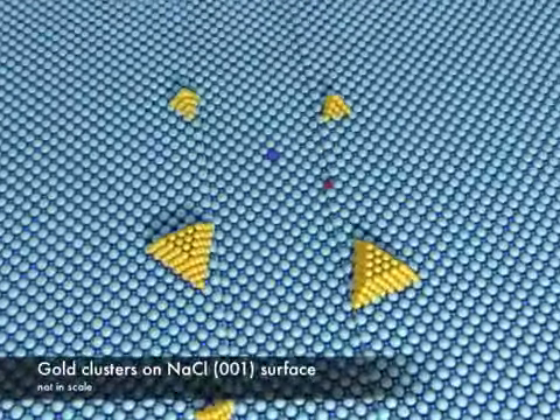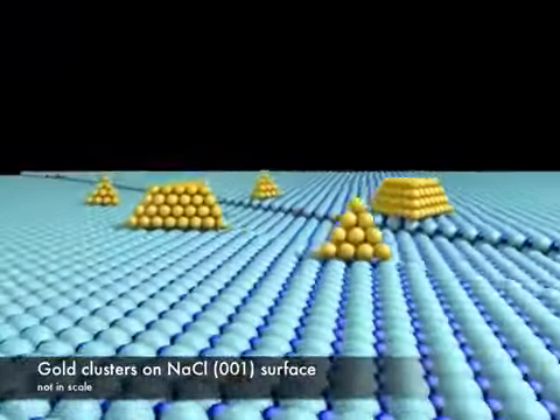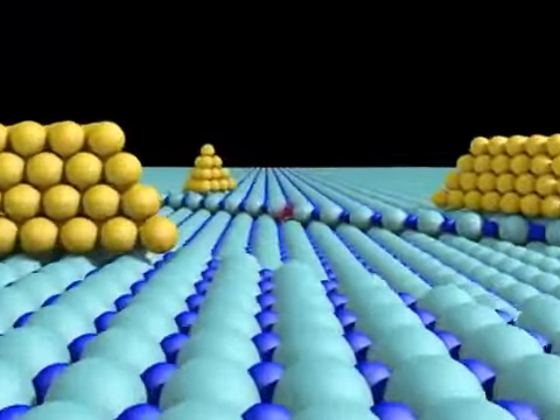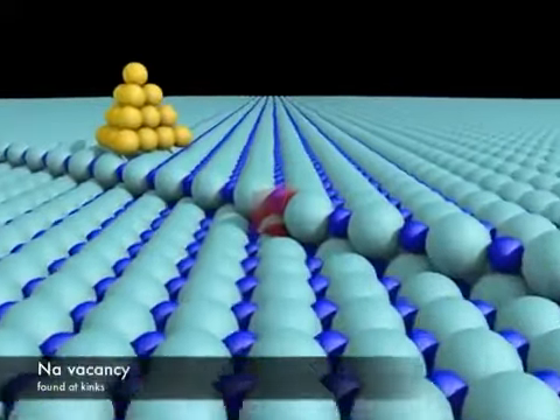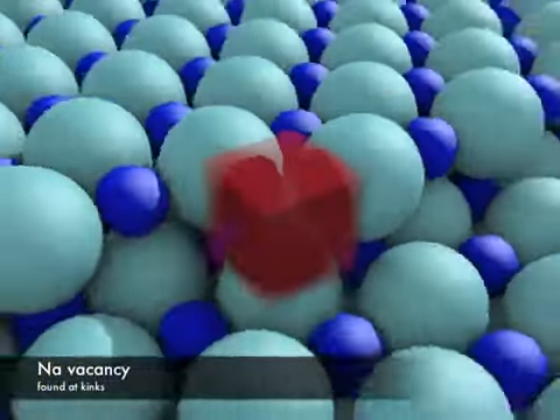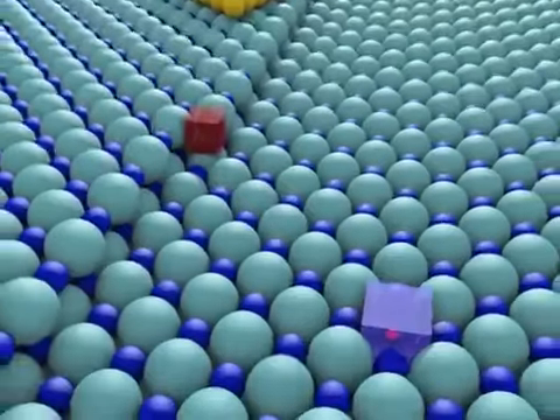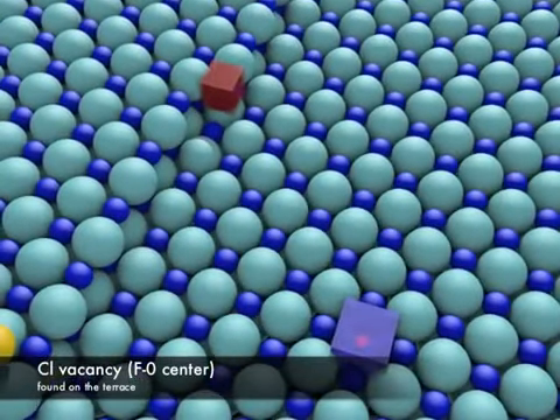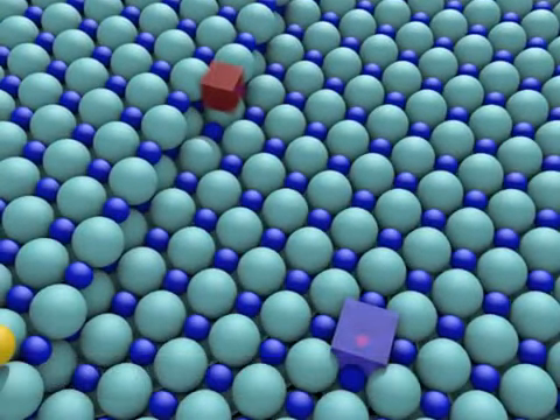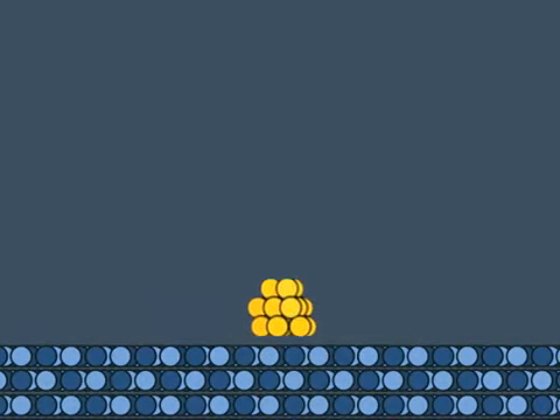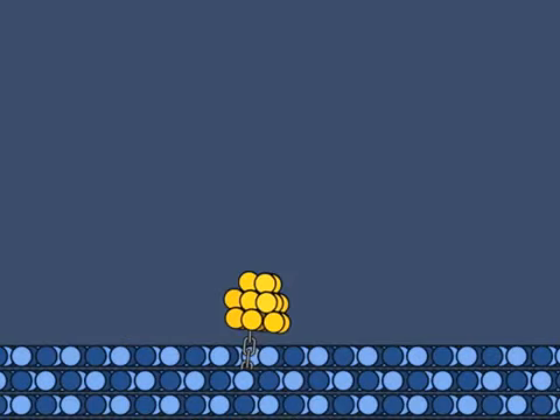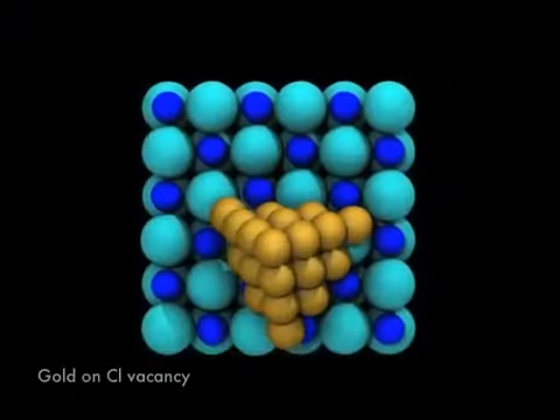Here we see a schematic representation of the system studied, gold on sodium chloride. As manipulation of clusters on such insulators is new, our study is also a proof of principle work. The cubes represent the common defects on the surface: sodium vacancies, missing sodium ions, at steps, and chlorine vacancies on the terrace. By simulating the system using quantum mechanical methods, we predicted that small gold clusters are mobile on the surface, but they will attach at the vacancies.